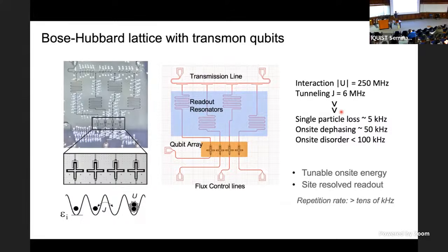Very good question, right? So this is one of the challenges. If you don't have particle number conservation, or if you have intrinsic loss, how are you going to prepare these states? And the bath engineering is kind of along that direction. Now, here, it's certainly true that it's pretty coherent to begin with. So within a short amount of time, you can still treat this as a particle number conserving system. But if you're thinking about longer times or larger systems, we are exactly going to use the engineered bath or the reservoirs as a way to populate this lattice, maybe even in the presence of dissipation, right? To stabilize the many-body states in a way.